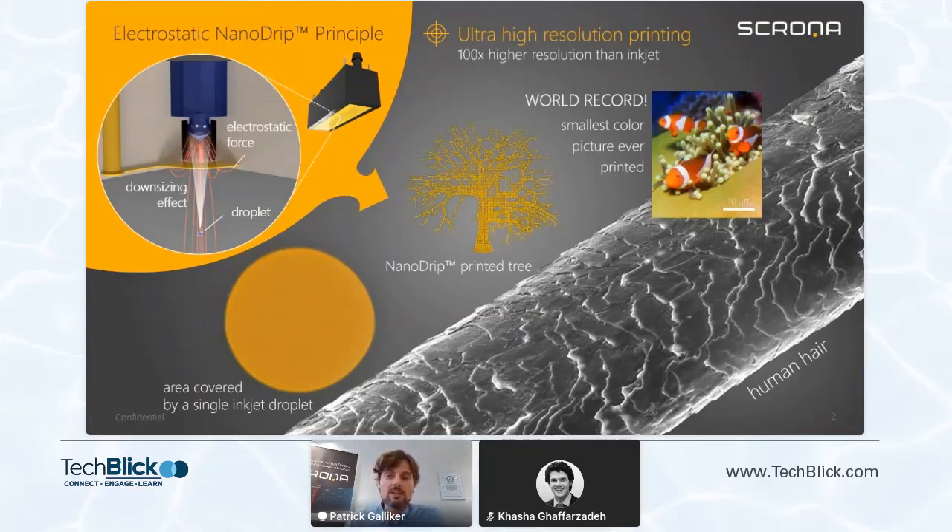One of them — notably this small picture with the clownfishes — has actually achieved a Guinness World Record for the smallest ever color-printed picture. You can see the scale there: this picture could actually fit onto the cross-section of a human hair. This picture, which relates to display technology, has been manufactured using quantum dots. The colors you see here are actually fluorescent, photoluminescent colors. We basically printed quantum dots at different locations in different quantities and then shone UV light at the picture. The combination of blue-emitting, red-emitting, and green-emitting quantum dots yielded this image in the quality you can see here.